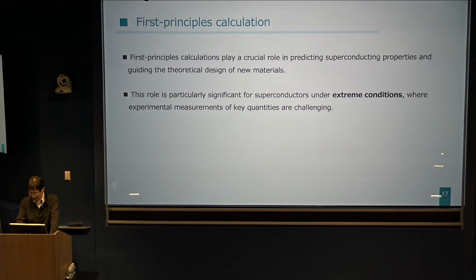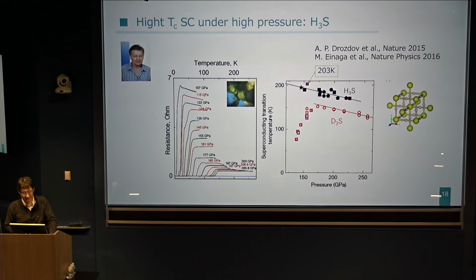The fact that the role of ab initio calculation becomes important has been demonstrated by the studies of hydrogen sulfide. For this compound, in 2015, the group of Mikhail Eremets reported that when we applied extremely high pressure, higher than 100 gigapascal, we can observe superconducting transitions at very high temperature. The maximum value is 203 Kelvin, which was the record of highest Tc.